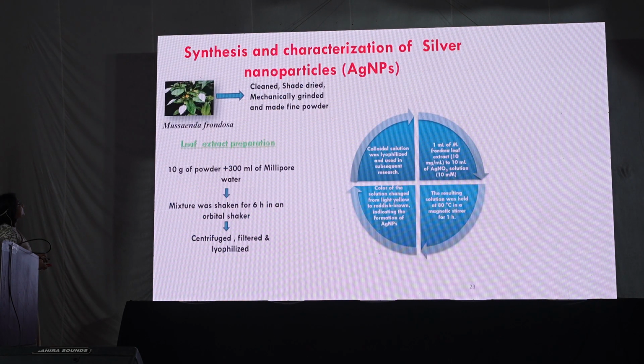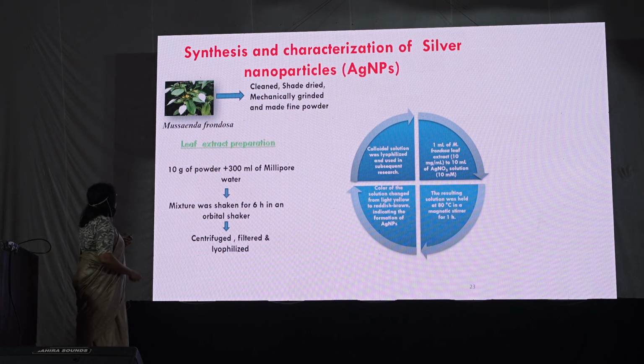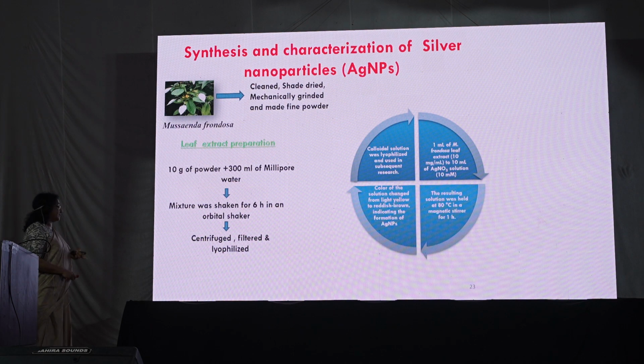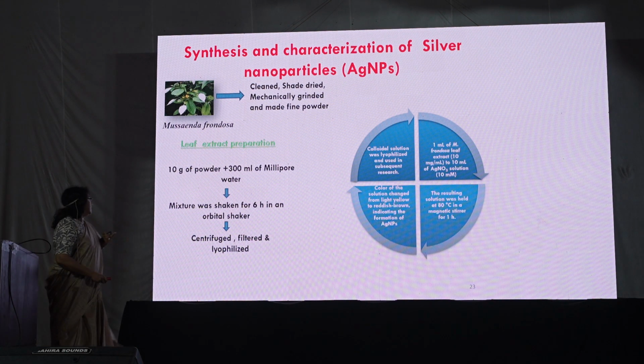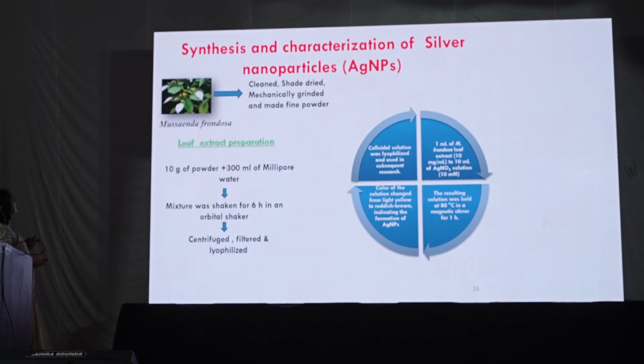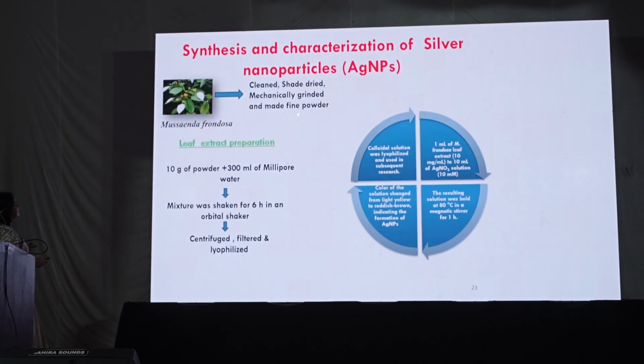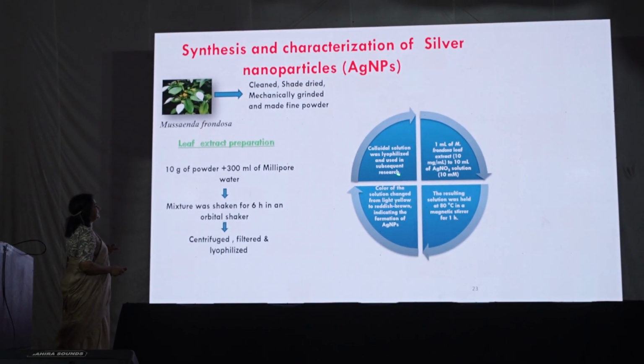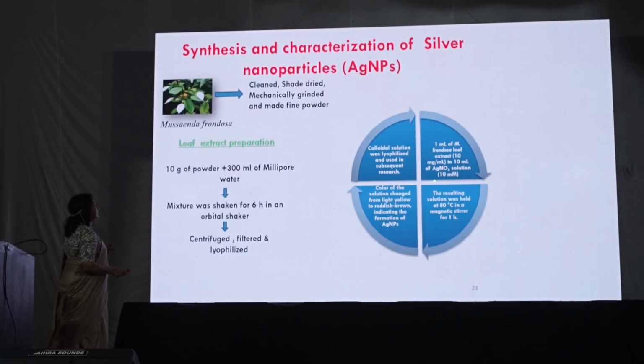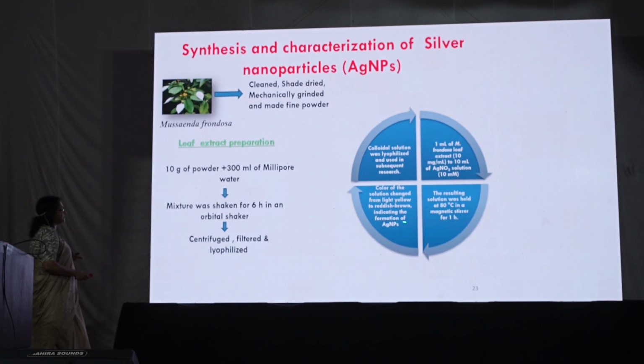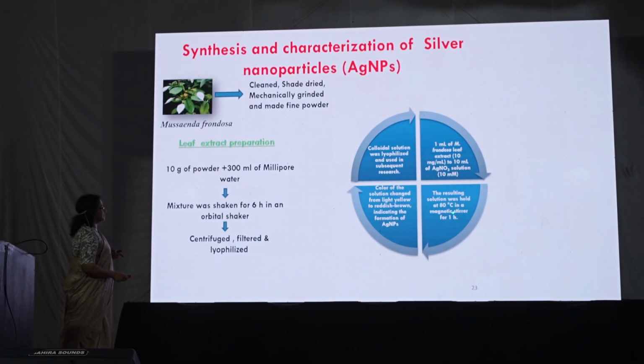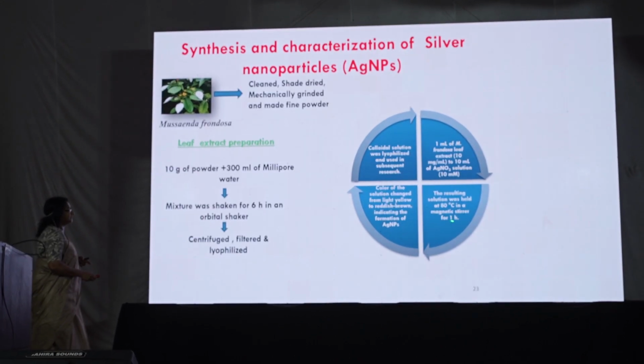Now moving on to the second part. Here we used a green synthetic method using plant extract, Mussaenda frondosa, whose leaves consist of a lot of phytochemicals that will act as reducing and stabilizing agents. These plant leaves were cleaned, shade dried and mechanically ground, and this plant material is used as a precursor material, and we have synthesized the nanomaterials. The colloidal solution was lyophilized and used for further studies, and this is mixed with the metal ion salt solution, and the color of the solution changed from light yellow to reddish brown, which indicates the formation of nanoparticles, and the resulting solution was held at 80 degrees for 1 hour for stabilization.